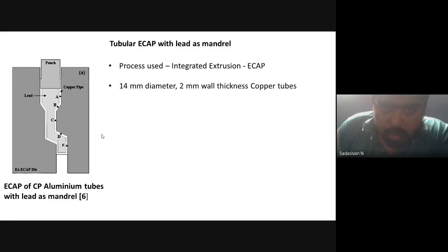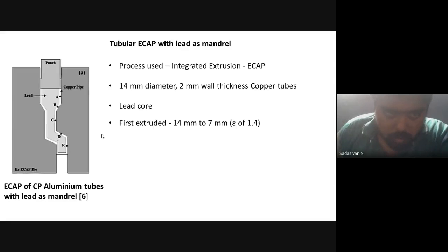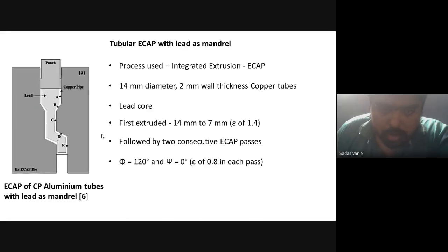14 mm diameter tubes, 2 mm wall thickness, lead used as core. Extruded from 14 to 7 mm in the first step, imparting a 1.4 plastic strain. Then 2 consecutive ECAP passes, each imparting a 0.8 plastic strain. The die used here has a channel angle of 120 degree and a corner angle of 0 degree, a very sharp corner. So the total cumulative plastic strain imparted here is 3. The higher the plastic strain, the better your strengthening, but along with that you will lose your ductility.